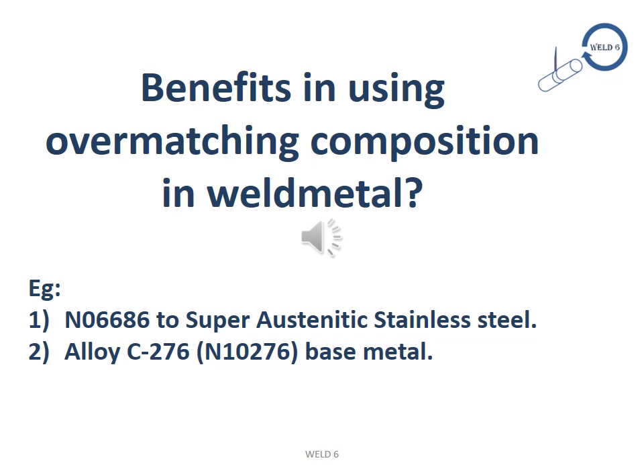An example is the use of nickel chromium molybdenum filler metal NiCrMo14, UNS number N06686, to weld the superaustenitic stainless steel alloys, those containing 4% to 6% molybdenum, and alloy C276, UNS number N10276, base metal.